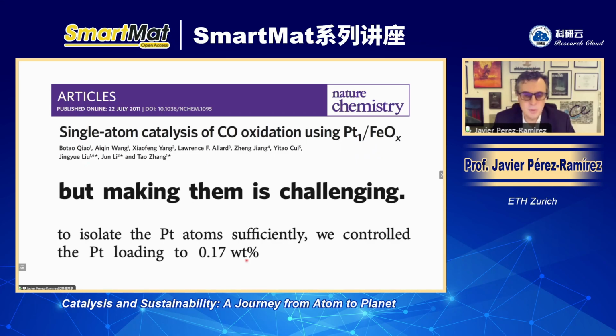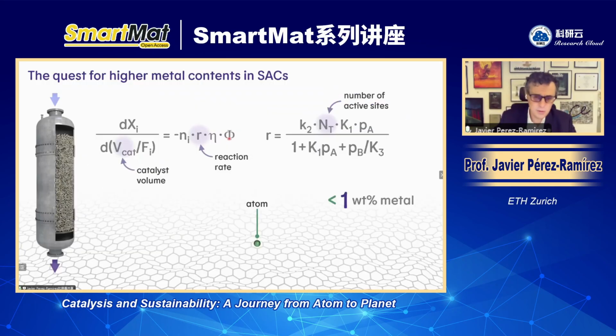So I have here two comments. We would like to have single atom catalysts with higher loadings without agglomeration. And we would like to use single atom catalysts for more complicated reactions, more high added value reactions than just CO oxidation, right? So progress in this direction has been done, and I would like to share that progress with you. The reason why we want to make single atoms with larger loadings is because we want to increase the number of active sites per gram of catalyst. And one way to do that is increasing the metal atom density. And the metal atom density, of course, is the metal loading.